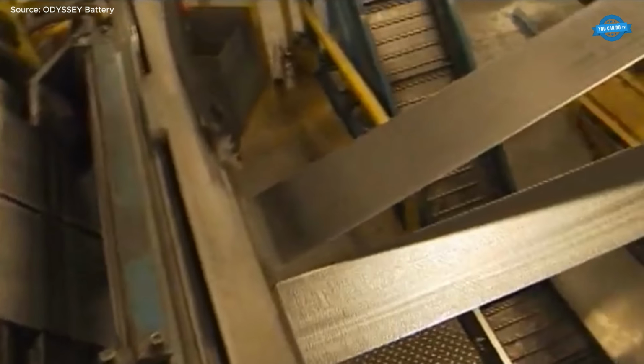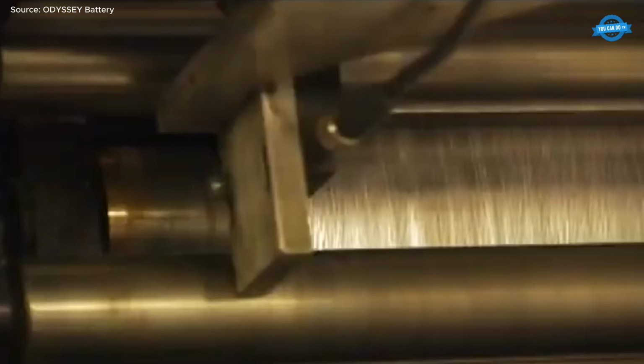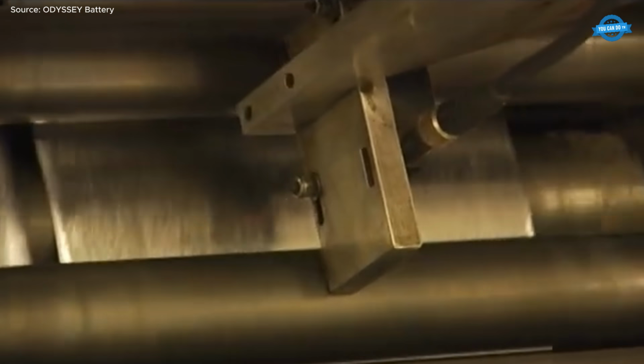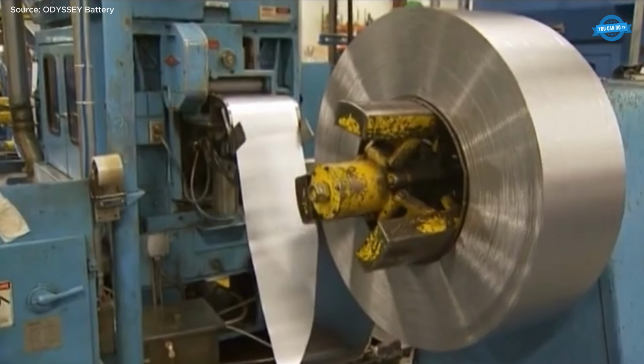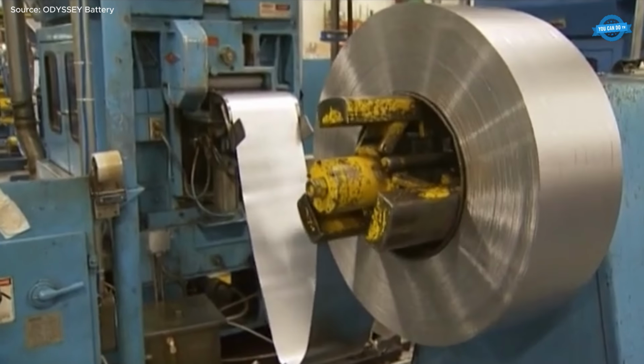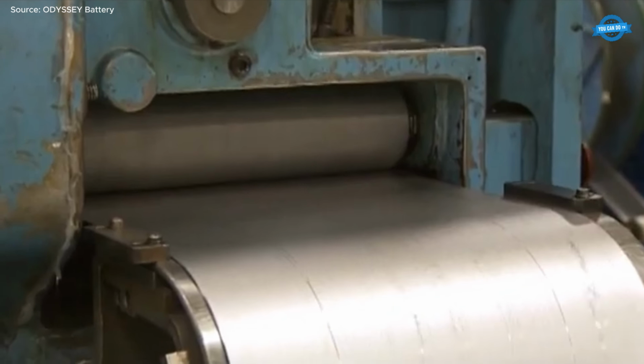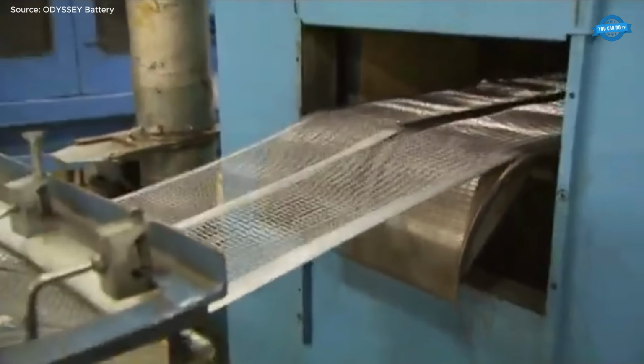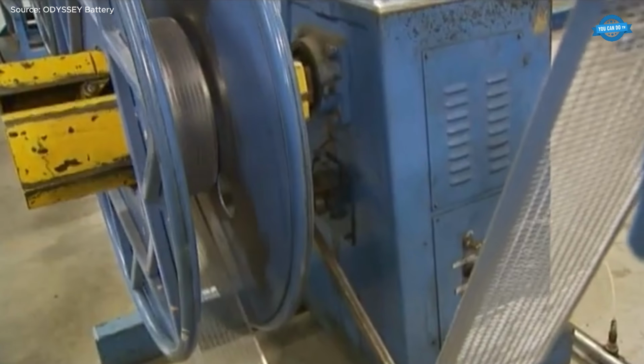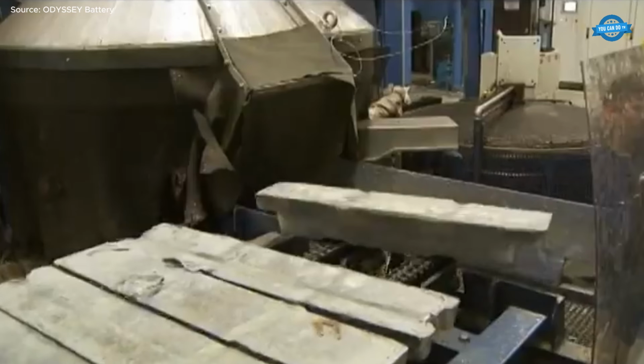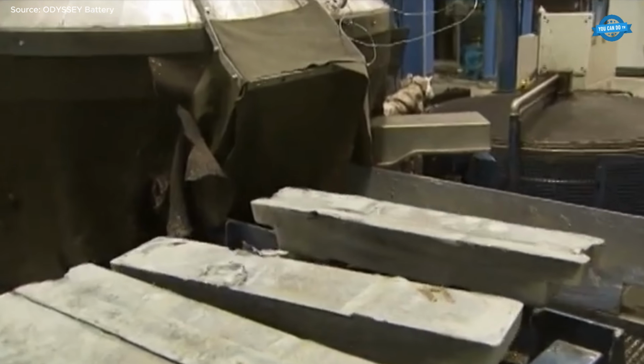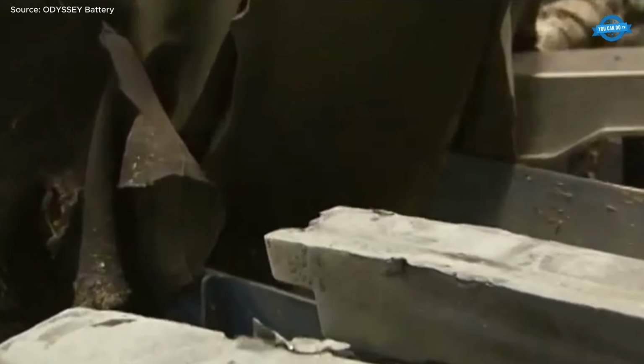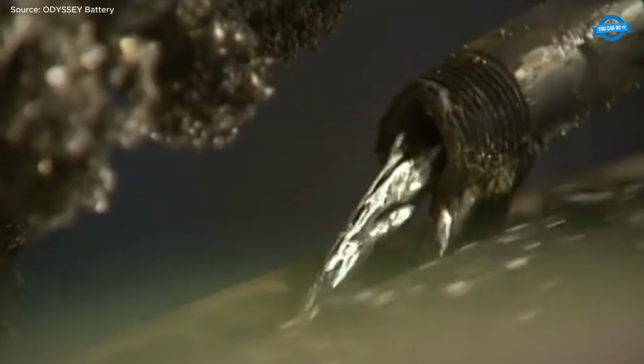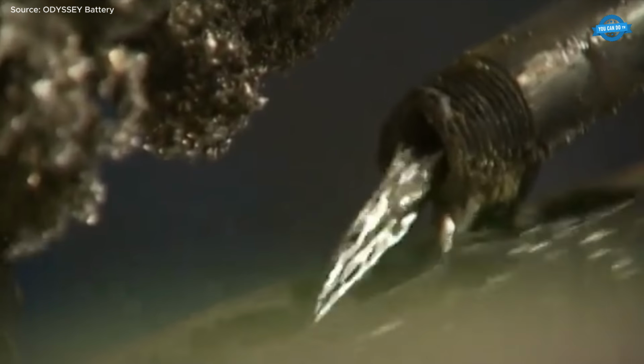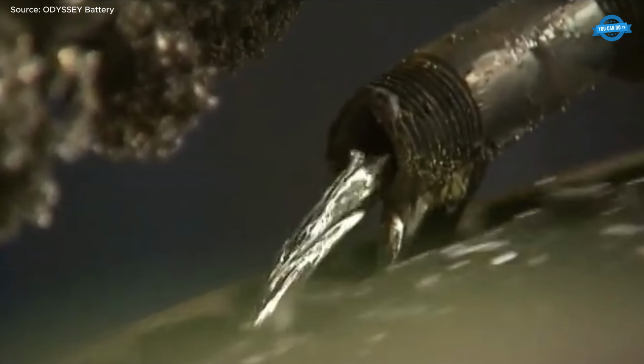The process begins with molten lead held at 750 degrees F, continuously fed into the chill casting line. Here, a refrigerated drum flashes the metal into a flawless 1 mm strip, its thickness monitored by laser with micron-level precision. That strip moves to high-speed perforation, punching the conductive grid pattern at nearly 1000 strokes per minute. Each plate is then pasted with carefully milled lead oxide, its weight monitored plate by plate, so only perfectly balanced components continue forward.